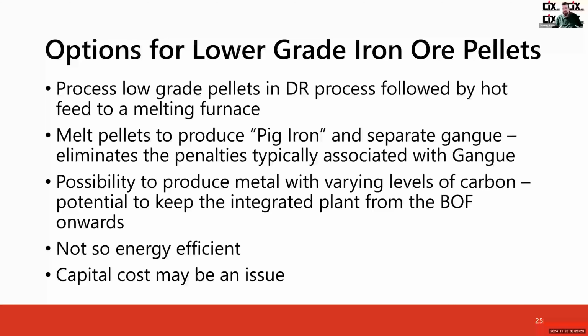Now, some people have started to look at developing a process flow sheet whereby you use lower grade pellets in a direct reduction process, followed by hot feed to a melting furnace, which does a very small amount of smelting. Essentially they produce pig iron in this furnace so that they can separate out the gangue into the slag and then use that pig iron hot metal downstream in the BOF. So essentially for some integrated plants, they would maintain the same process flow sheet and just replace the blast furnace, coke oven blast furnace, with a DR shaft and one of these smelting furnaces.